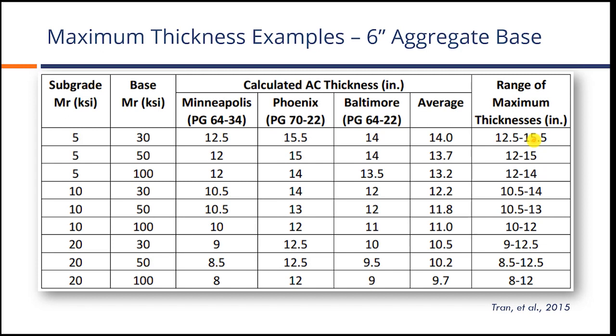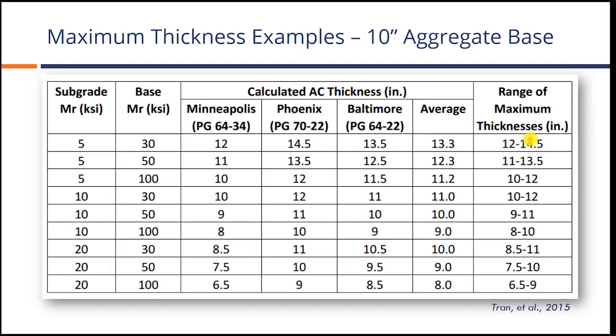We're not talking about 20-inch pavement sections. We're not talking about 3 or 4-inch pavement sections either. We're in that range of about 8 to about 15.5 in this particular case. If we look at a 10-inch aggregate base, again, same set of conditions here, the thicknesses come down a little bit because we have more aggregate base. There's more pavement structure underneath the asphalt. Now the thicknesses drop. We're down around 6.5 up to about 14.5. But again, we have a working range.